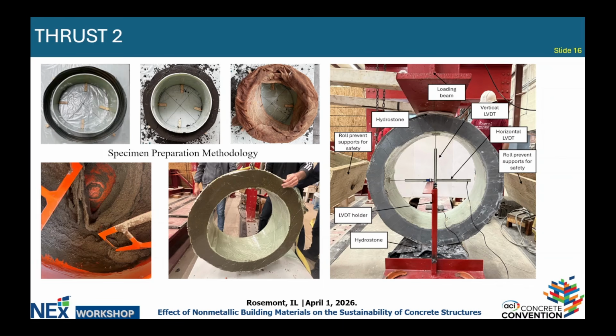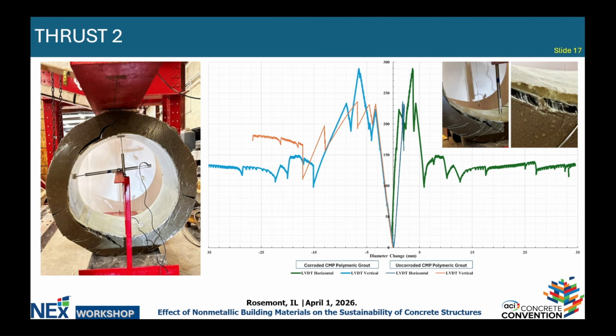And this is the test setup that we conducted with a 2-point bending and having an LVDT in the vertical and horizontal to sort of get this effect of how the deflection is in the slip liner and the overall composite pipe in the horizontal and the vertical directions. So if you look at these results here, you see the vertical and the horizontal displacements for the corroded and the uncorroded, the comparisons.